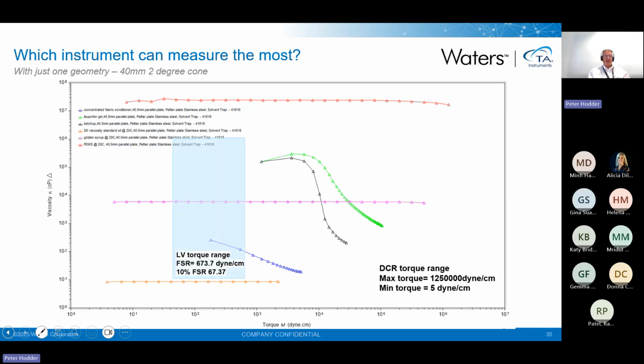Now, if I start to look at the LV, again, what I've confirmed is I can't measure the low viscosity, and I can just start to see perhaps the low shear end of the concentrated fabric conditioner. Maybe I get 2 points to hint that it's shear thinning, but I don't get anywhere near the ketchup or the gel. If I go to the RV, then maybe I'm moving more towards actually starting to see the structure of the viscosity in the bottle for the ketchup and the gel, but I can't measure much more of the shear thinning. So I don't get any idea of whether it changes much. In fact, I might have even come to the conclusion it was Newtonian, because I don't get much of that hint of that drop in viscosity.